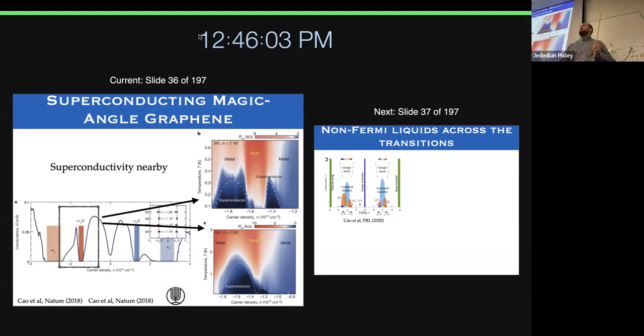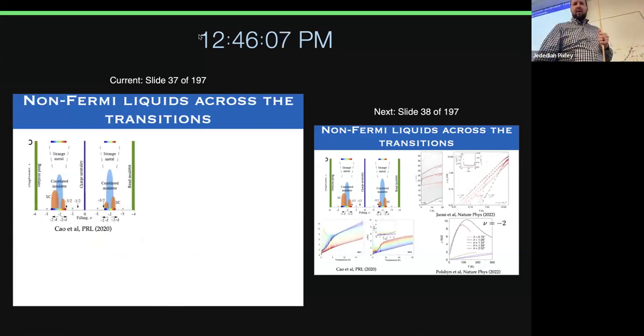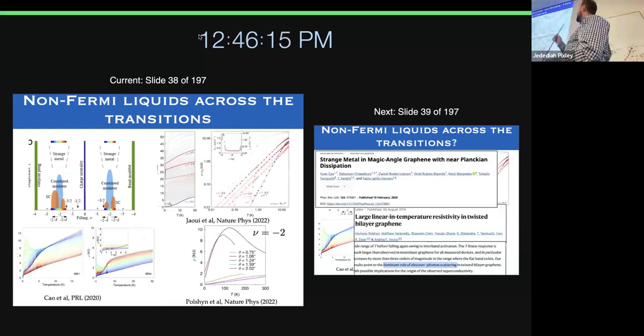Let's now look for this non-Fermi liquid scaling. And it's going to tell you where this field's at in this regard now. Looking across this insulator, you can look at the resistance, and several groups have now seen a linear T resistivity. So this is resistance versus temperature, and there's roughly a regime where it's linear. These authors say this is due to strong correlations. These authors say it's due to phonons.